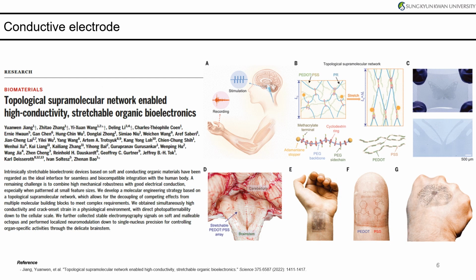Third, to obtain high-quality signals in the long term, the electrode should have high conductivity. Essentially, higher conductivity of the electrode leads to less loss of biopotential signal transferred from the human body to the device, allowing for accurate electrophysiological signal recording in the long term. The paper produced an electrode with high conductivity and stretchability by doping the conductive polymer with PSS.